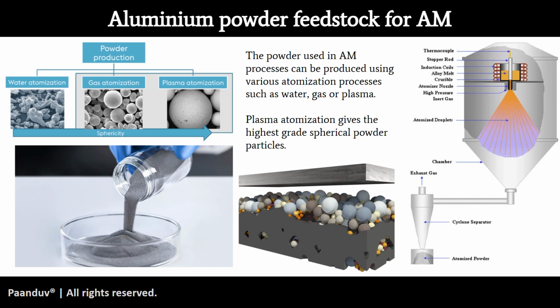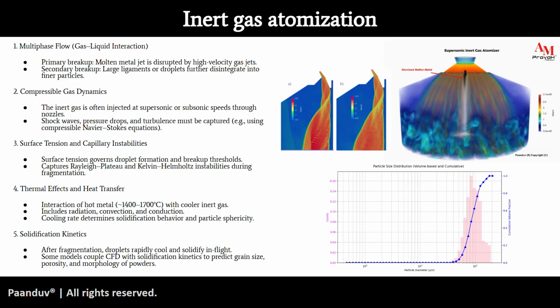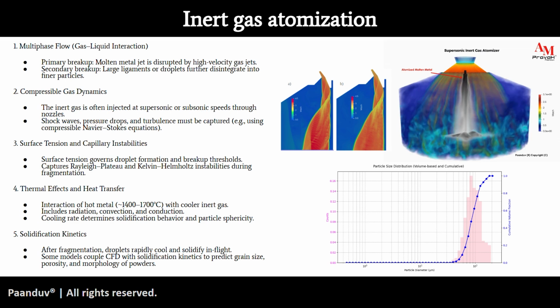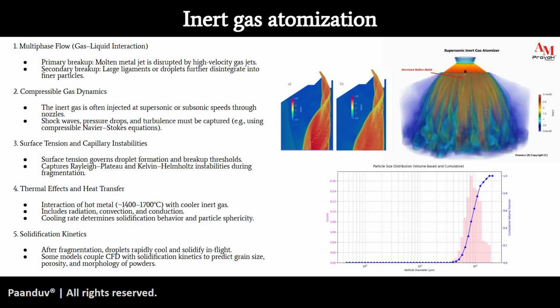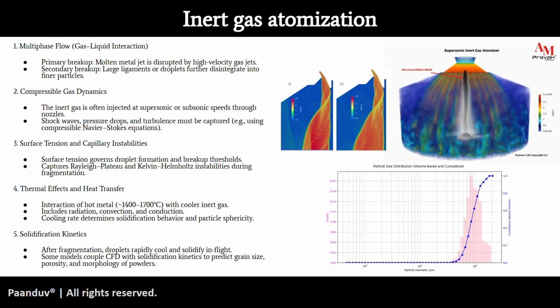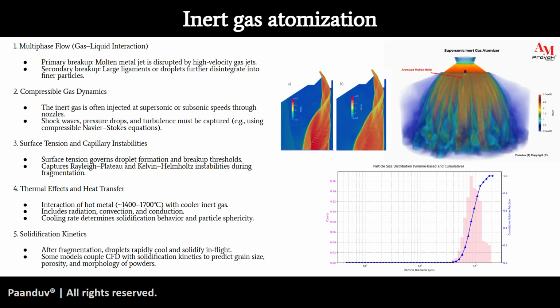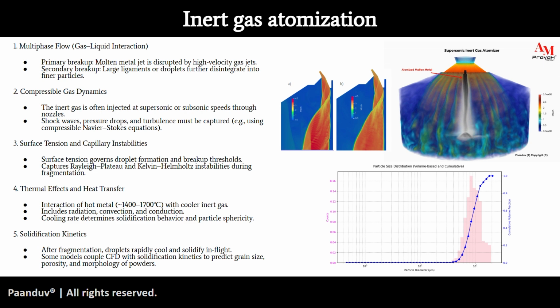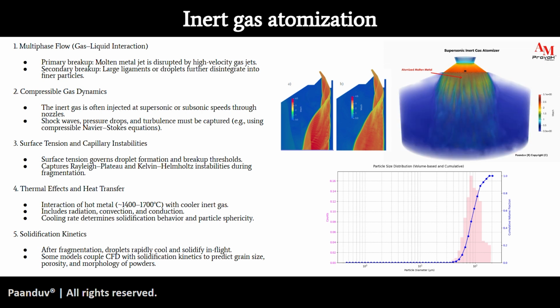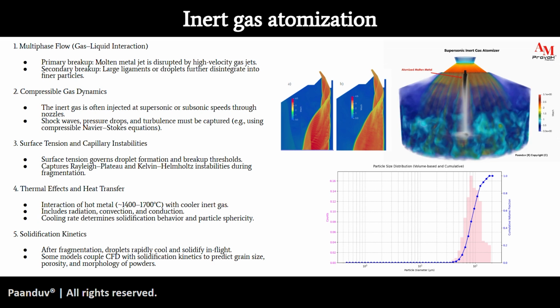But another application of AM PravaH is direct atomization simulations as well, because even if you have an atomizer, gas, plasma or water atomizer, it is quite tricky to adjust its process parameters so that you get the desired sphericity. To that effect, we have also done some work on supersonic inert gas atomizers, where you have a small molten metal block in the center, and you have Mach speed 4 up to Mach 4.5. At that speed, your inert gas is impinged onto this metal block, and that atomizes the particles. If you look at the bottom plot, you can see the powder size distribution that you have obtained after this atomization process.